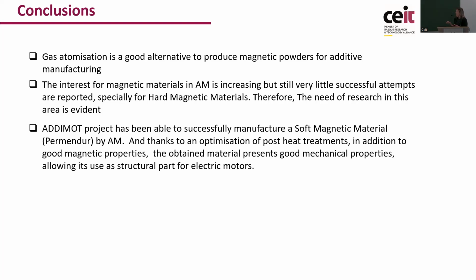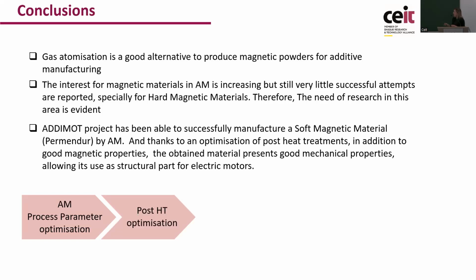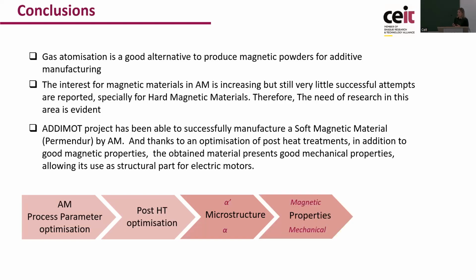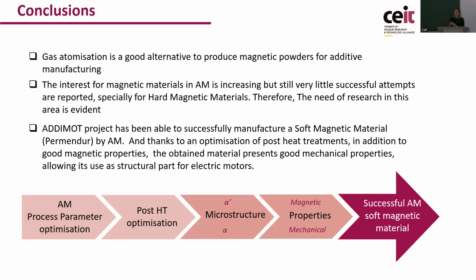In our case, in the Addimot project, we have been able to manufacture a soft magnetic material and then process it by SLM or laser powder bed fusion with optimized parameters. And then thanks to the heat treatment optimization, we have been able to tune the microstructure of this material, achieving both magnetic and mechanical properties. So the final component was able to be applied with even structural properties. And thus we can say that this project has been successful in terms of this material optimization.